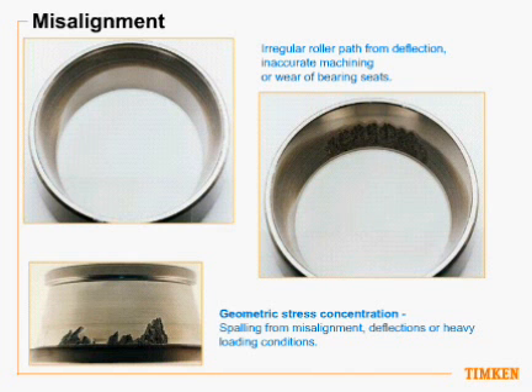And if you'll notice the roller path, you can see that by the oil staining there, that it's not riding on the center of the raceway. It's actually riding from the small end to the large end. What this is showing me is that there could be a number of things, but it could be inaccurate machining, which I would assume that any part that we're working on, the original component we took out would have shown this also. But the cup might not have been seated in the hub correctly, which will cause this misalignment. Okay, it's actually where the cup and cone are not seating together. One is askew of the other.